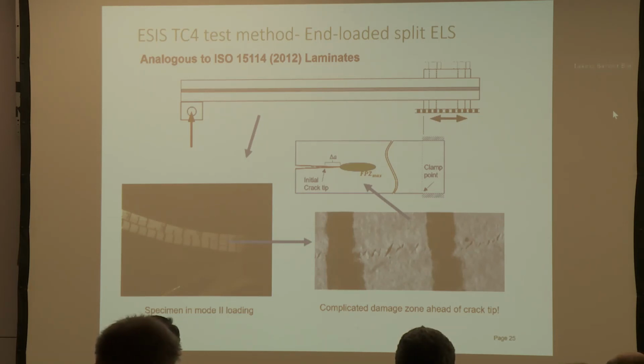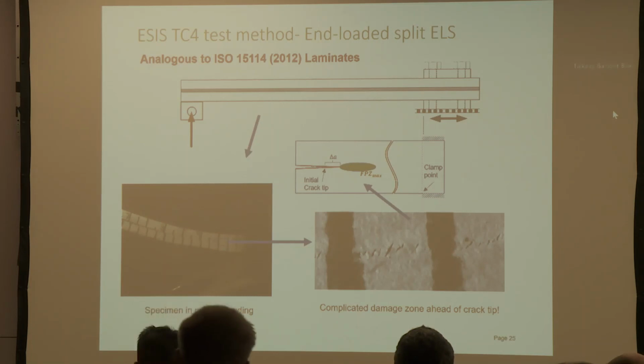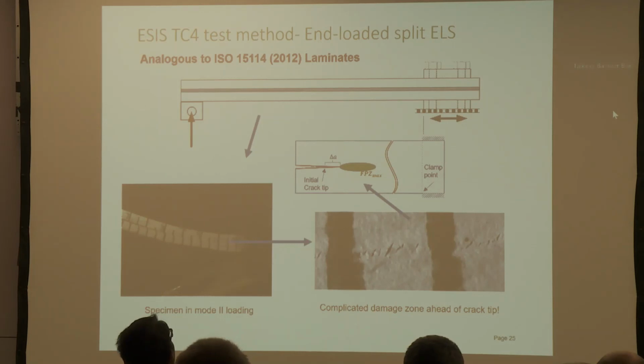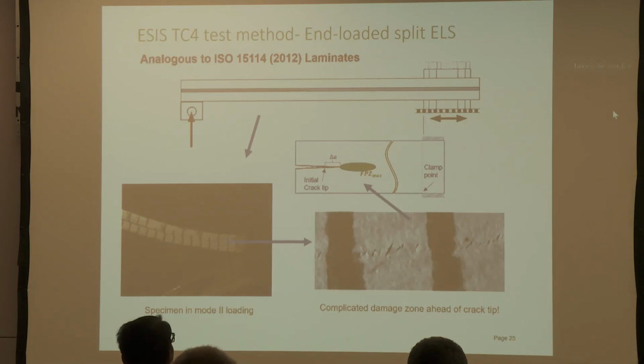So locally, of course, what's happening here is more akin to Mode 1. Globally, it's a Mode 2 fracture phenomenon. And of course, there is a large energy dissipation associated with it. So one school of thought says, don't go here, measure Mode 1, and that's all designers need to know. And another school of thought, which is closer, I think, to where I stand, is that this is a real phenomenon, and the combined response of all of these Mode 1 micro cracks, if you like, leads to additional energy dissipation, which we need to know about. If we're interested in conservative designs, then we want to be able to take this into account and measure it reliably.